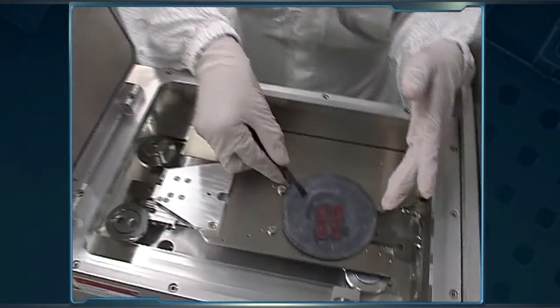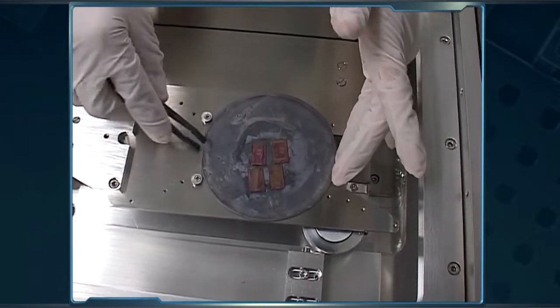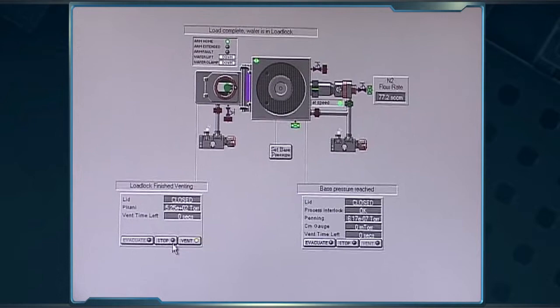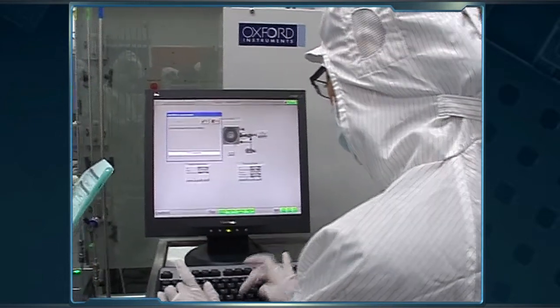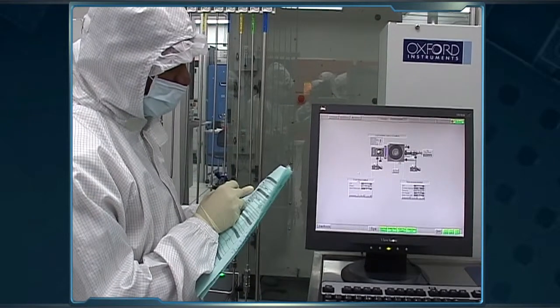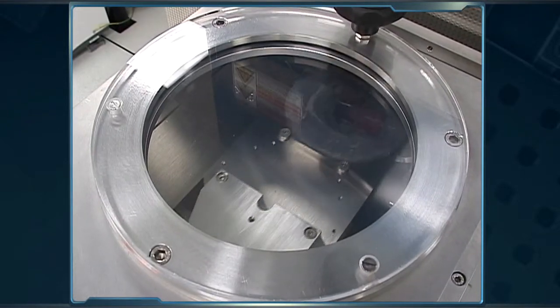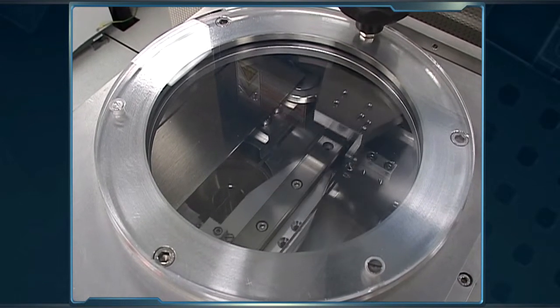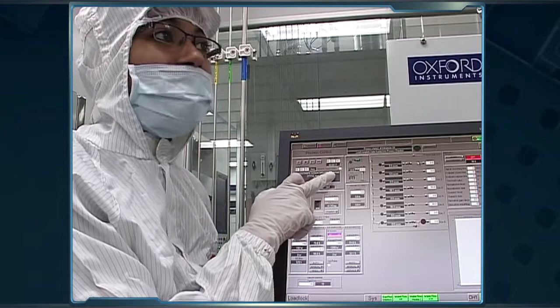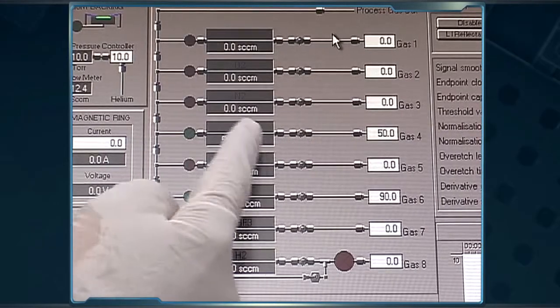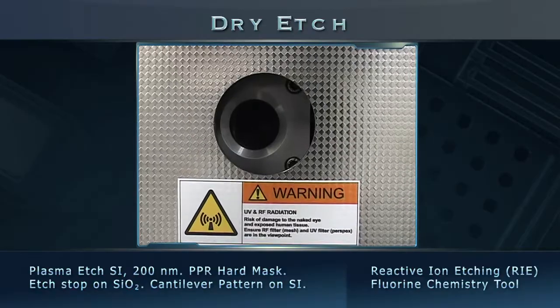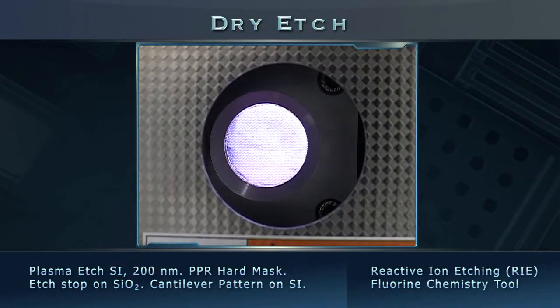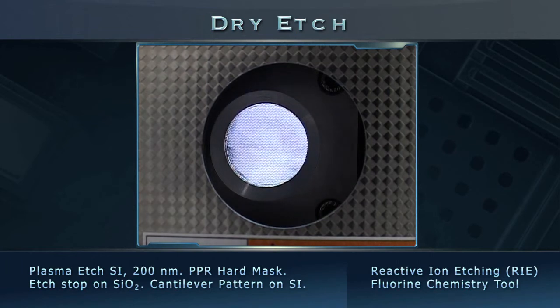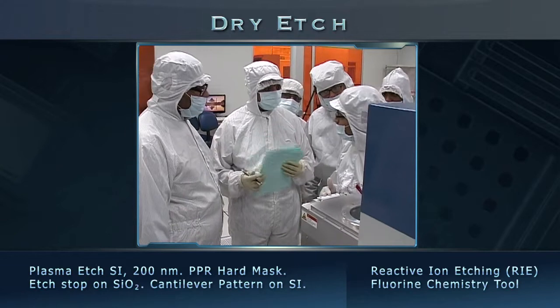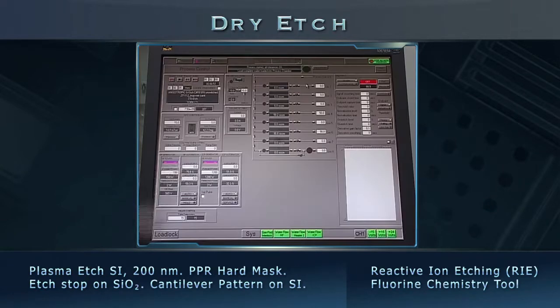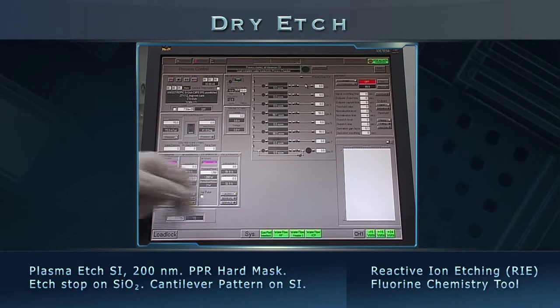We now load the samples into the RIE station load lock chamber. Next, using the graphical user interface of the station, we create a vacuum in the load lock. Then the samples are transported into the RIE main chamber. Gases start flowing inside the chamber at specified flow rates and temperature. Plasma strikes when appropriate conditions are reached. For our device layer of 200 nanometers, we have specified an etching time of 2 minutes.